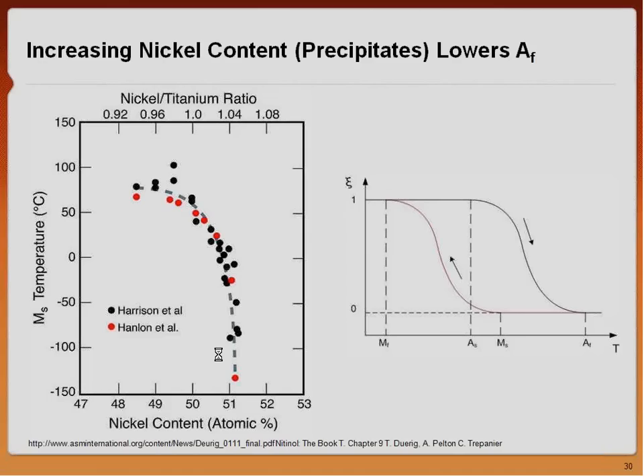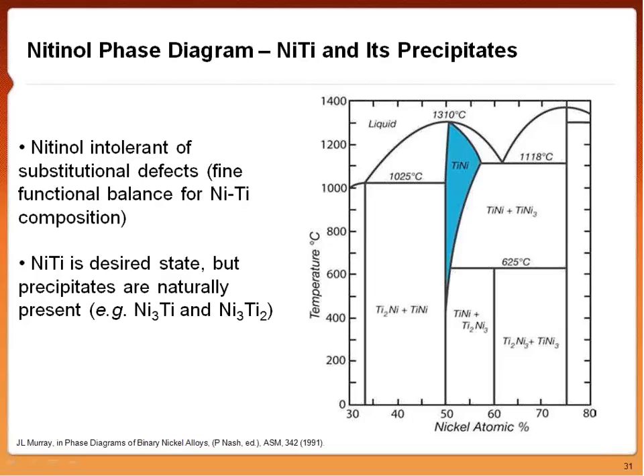So the way this works is we go back and look at the phase diagram for nitinol. This is a typical phase diagram, so we have atomic percent nickel on one axis, temperature on the other. And we can see that nitinol is only stable across a certain range of nickel percentage and temperatures. It's very intolerant of substitutional defects. Deviating slightly gives us these nickel-rich precipitates, Ni3Ti or Ni3Ti2. This notation is just what some of the papers say. They switch the titanium and nickel around, but it's one and the same.